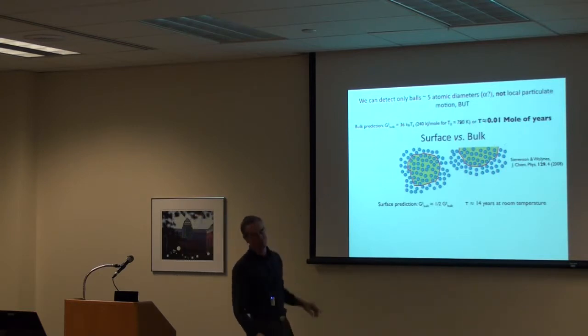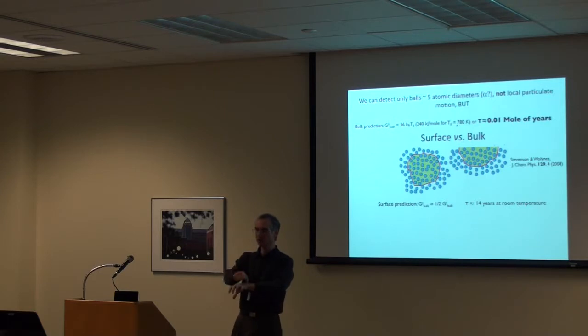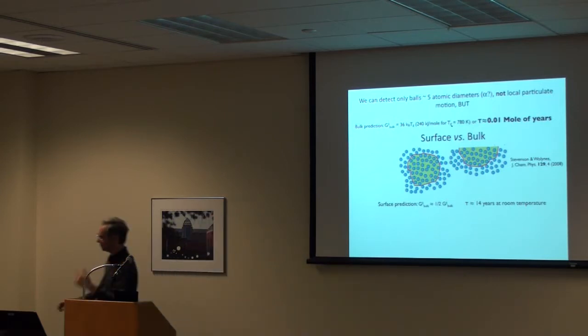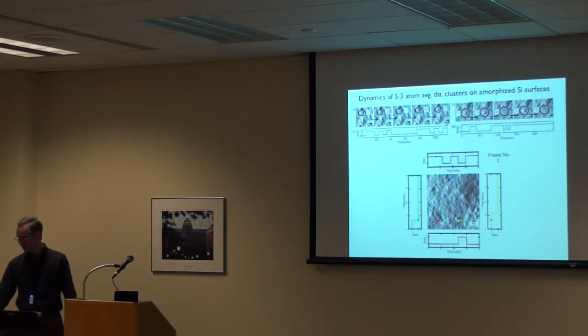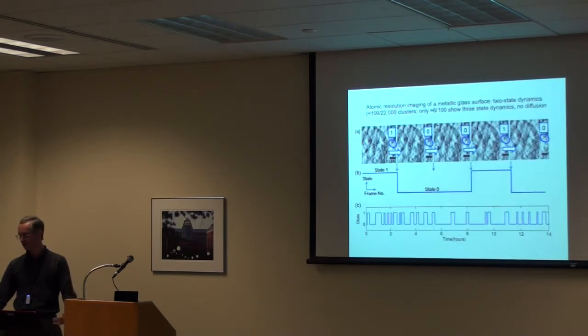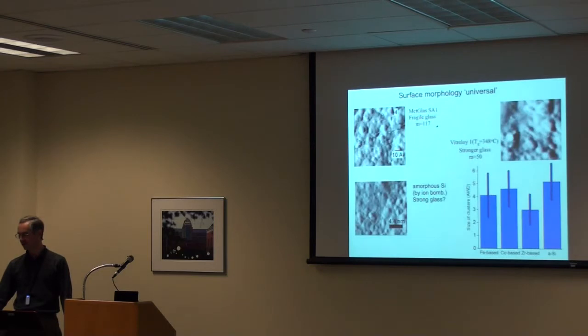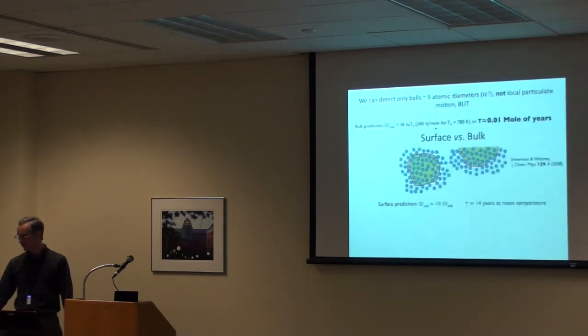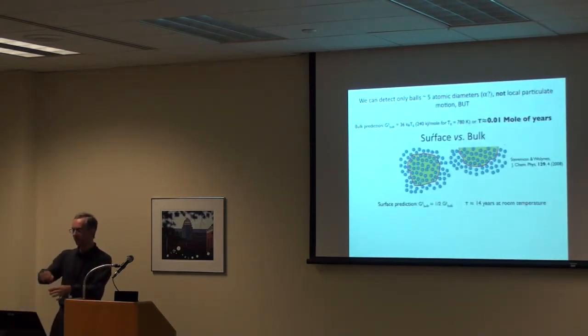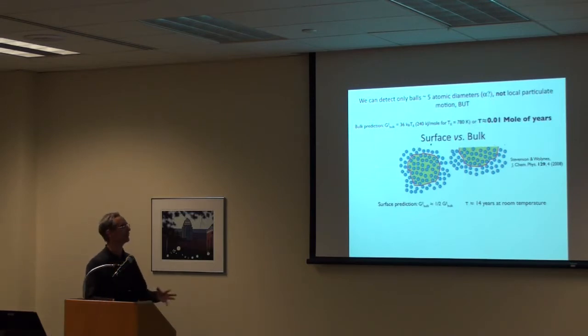Now, the prediction from the bulk, though, is for how long, how fast should this hopping be? I'll go back to one of these movies for a second. You can see there's a time scale of minutes on these axes, and the same was true for all the other movies I was showing you, minutes to hours. Basically, it takes these balls somewhere between a few minutes to an hour or so to hop back and forth. That's the kind of kinetics that we have to explain.